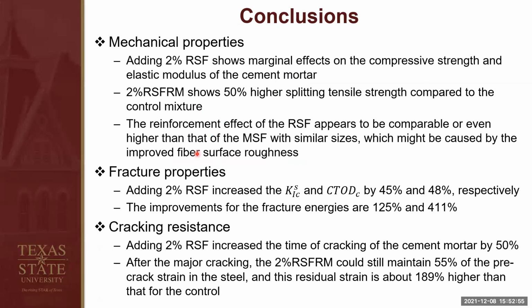Here are some conclusions for the mechanical properties. Adding 2% recycled steel fiber shows little effect on the compressive strength and the elastic modulus for the cement mortar. However, we achieved 50% split tensile strength improvement by adding 2% recycled steel fiber. And the reinforcement effect of the recycled steel fiber appears to be comparable or even higher than that of the manufactured steel fiber with similar sizes.